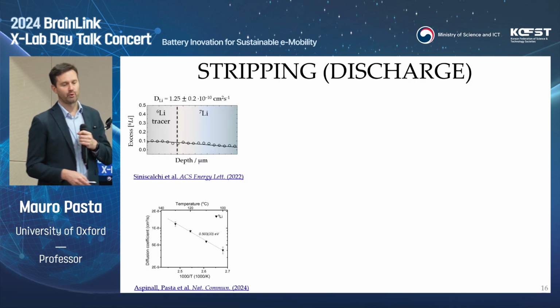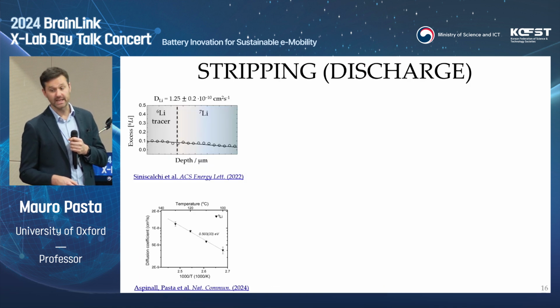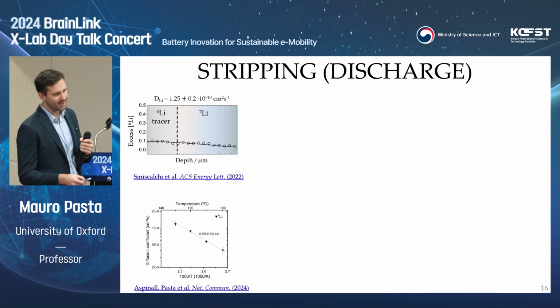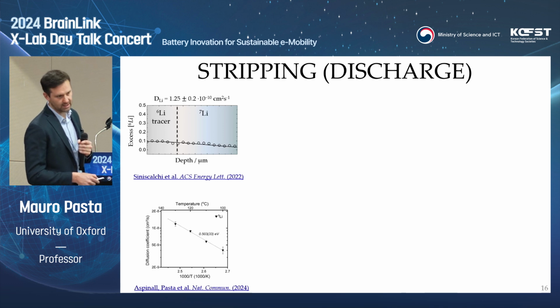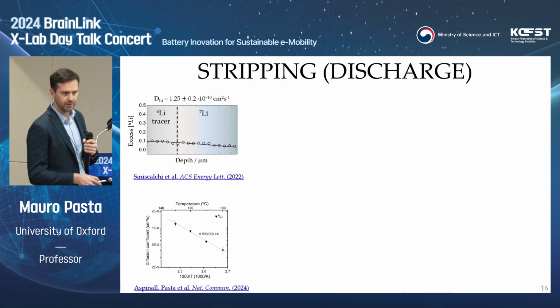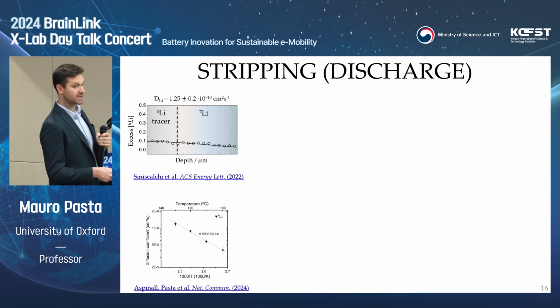Now, what does transport of lithium within lithium mean? Well, you have two main mechanisms. One is vacancy diffusion, which I think we should all be familiar with. We characterized this diffusivity in quite a level of detail. We used a couple of different techniques. This is a PFIB SIMS experiment, secondary ion mass spectrometry.